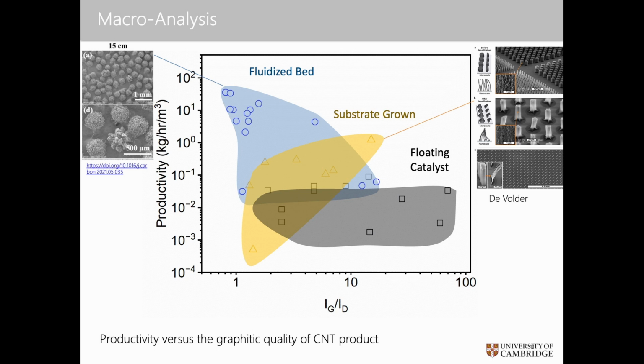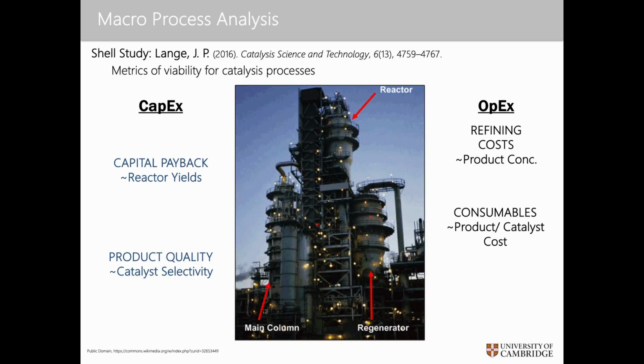And so what these materials are, they're extremely long nanotubes. So each individual nanotube might be hundreds of microns to a millimeter long. And that's far and away differentiated from these other processes that just don't grow that long of nanotubes, and certainly don't grow them at the same rate. So that is why there's interest in this process, particularly in that, everyone that I showed on that early plot are running this floating catalyst process rather than one of the others. And so, I've been working on this a while, kind of 15 years almost now. And what has emerged is not only kind of a scientific rationale around this, but some economic rationale.